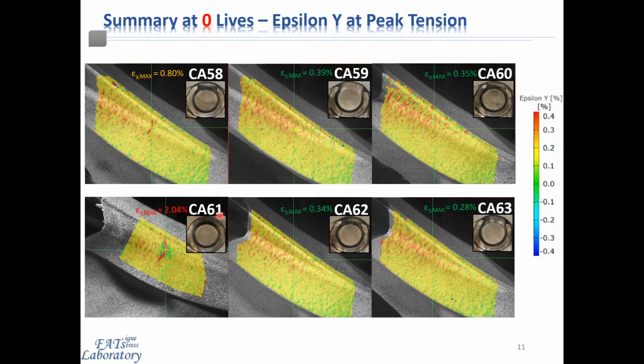Here you can see the axial strain in the critical region of each of those 6 components during the very first tensile reversal in the fatigue loading. The contour plot highlights in red any regions of the component which exceed 0.4% axial strain. You can clearly observe in certain regions of the forging there is already strain localization indicative of an incipient crack. So on these 2 particular forgings, that's quite obvious. This crack is due to poor fusion in the forging process, which I'll discuss in more detail a little bit later.